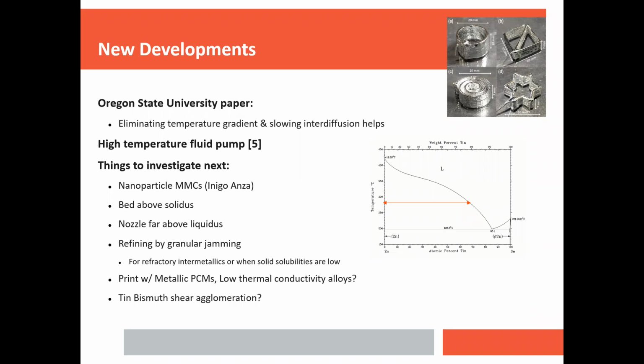So in terms of more common metals like steel? Yeah, steel, for example. First off, aluminum, I mentioned aluminum with a titanium diboride coated titanium nozzle. You could, for example, with iron, with steel alloys, engineer a cubic BCN composite. So it's like a boron nitride that's doped with sufficient carbon that it still wets but doesn't dissolve necessarily in the steel. So you could envision something like that. And for titanium alloys, I don't know. There's a lot of room to play around.